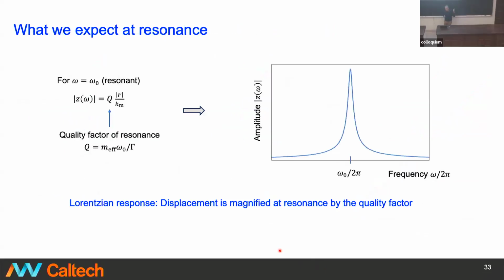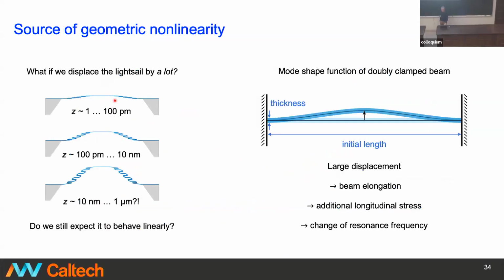Everything I told you so far was about excitation far off the resonance at low frequencies. These resonators have resonances typically in the range of 10 to about 50 kilohertz, and they're quite unusual resonators. Most resonators with frequencies that high are pretty rigid, pretty stiff, but because of these springs, we have a very compliant structure that has quite a high quality factor. If I excite at resonance, I get a displacement amplitude that is increased by approximately the quality factor. So the question is, what happens to this structure if I displace it at resonance?